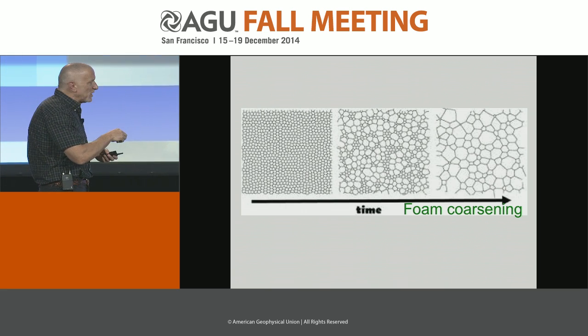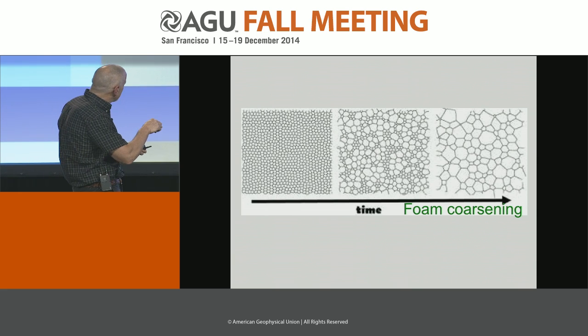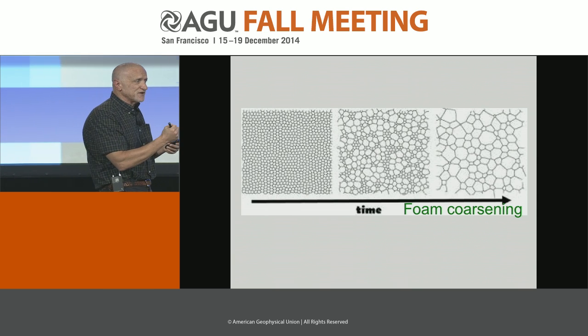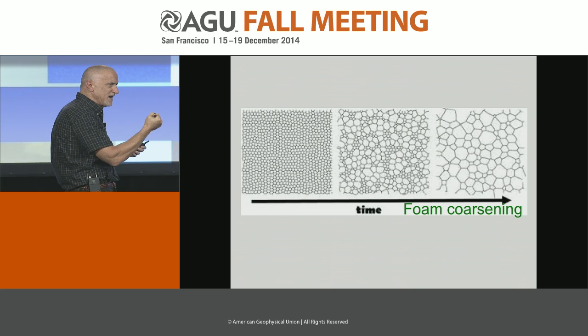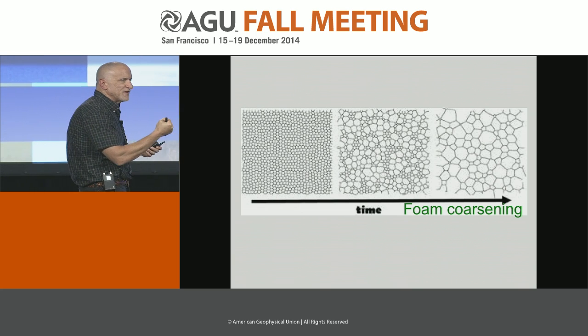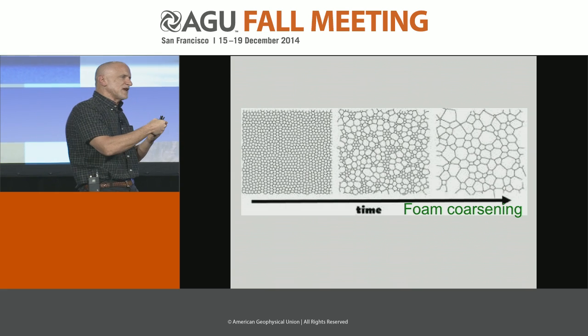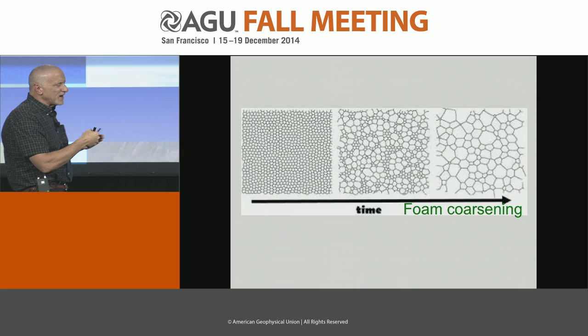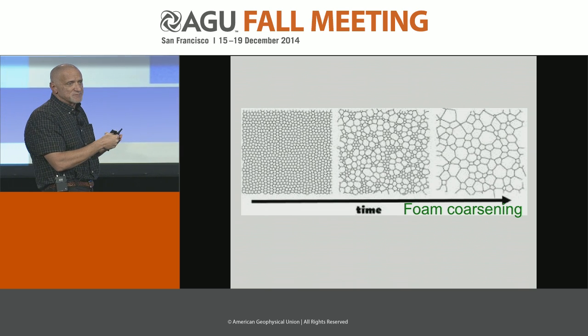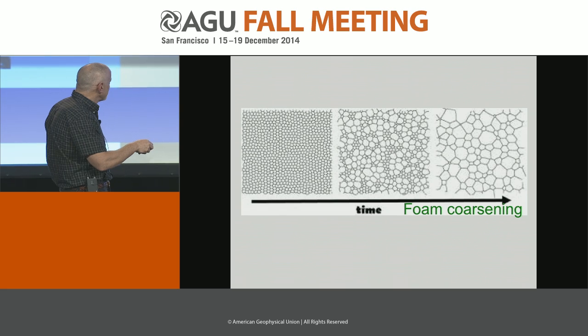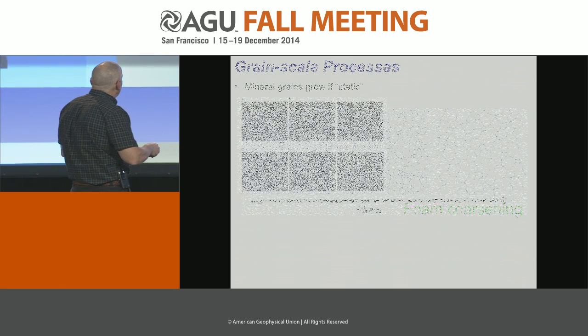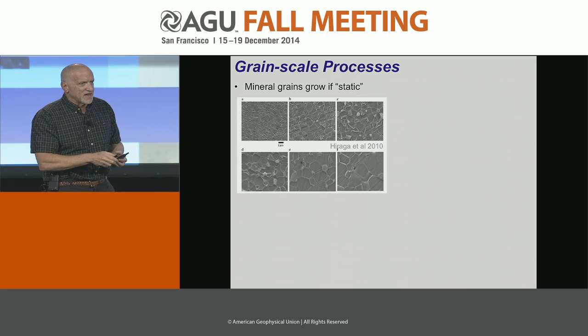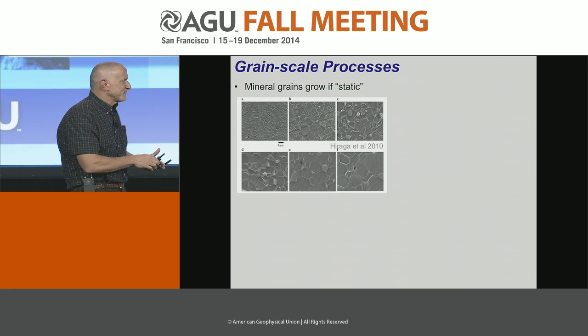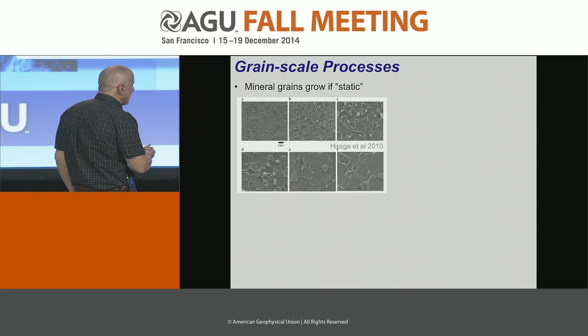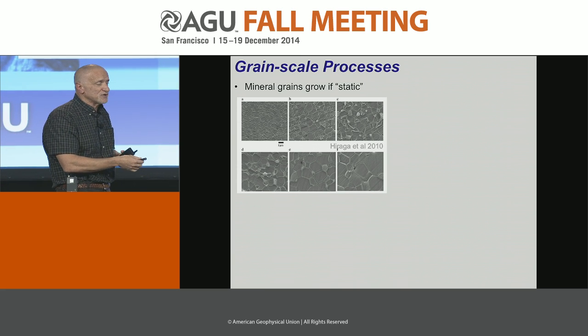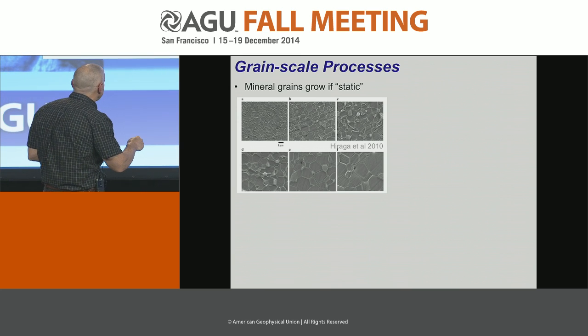In effect, the big bubbles are eating the small bubbles, because the small bubbles have a very high surface tension in them. They have very high curvature. They're being squeezed by the surface tension, so the pressure on them is high, and that high pressure squeezes them into the bigger bubbles. So in a sense, that's how the big bubbles eat the small bubbles. Well, grains in rocks effectively do the same thing, more or less. It's more complicated, but the idea is the same: you're going to a lower surface energy state by going from small grains to big grains.